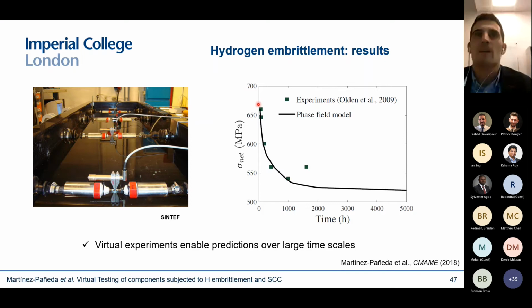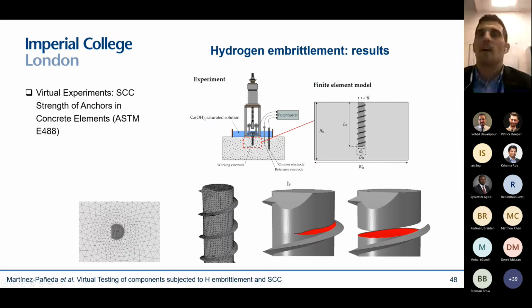But the good news is that we can take our model and first reproduce the experimental data, and then run very large virtual experiments over very large time scales. There we can tell them the critical load below which you can subject your structures safely. We can do anything that we want. For example, we can optimize experimental campaigns. We can run standardized tests.